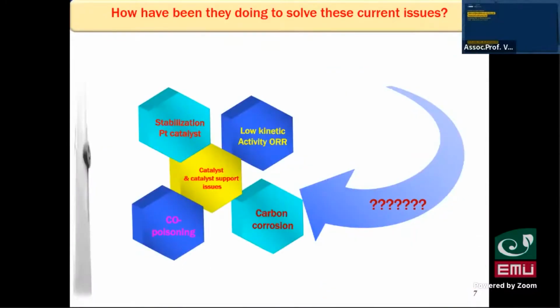So how do they address these current issues? As I just mentioned in the previous slide, they try to enrich the kinetic activity of ORR. They try to find ways to stabilize the platinum catalyst on the carbon support. They also modify the carbon support, and they have ideas to reduce CO poisoning and carbon corrosion. These are some ways scientists try to apply solutions.